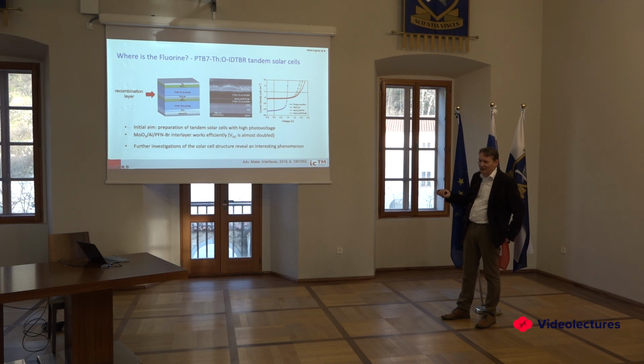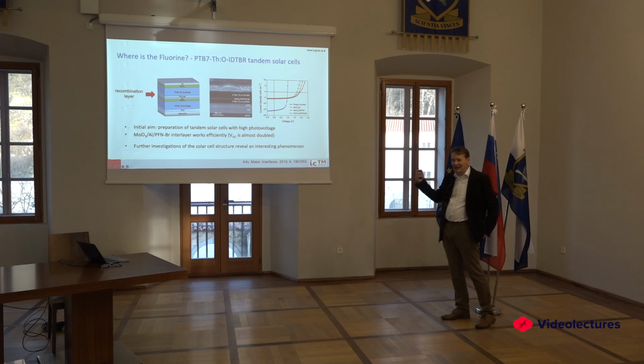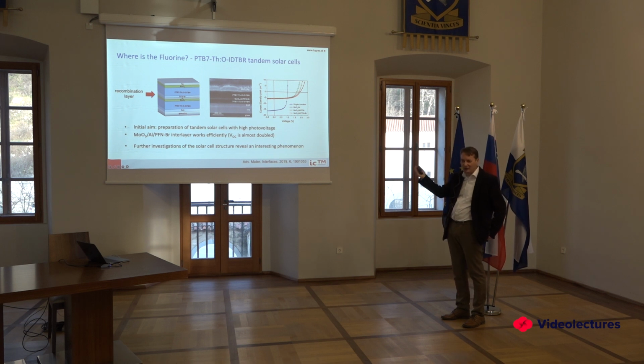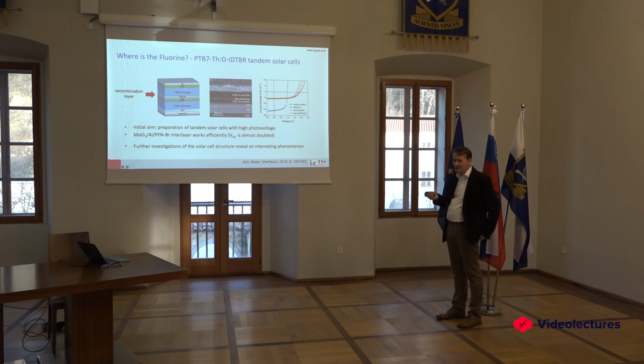But nevertheless, what we found out by this, so actually we wanted to do something totally different. We really wanted to make a tandem solar cell, and just wanted to analyze it if we have a nice cross section, and we used here a molybdenum oxide aluminium layer, and aluminium is also sometimes used as back contact, as electrode, because it's very cheap. It can be evaporated easily. It can also be printed in some cases. Printing is not so easy, but it can be easily evaporated. So it would be a cheap material as back electrode.